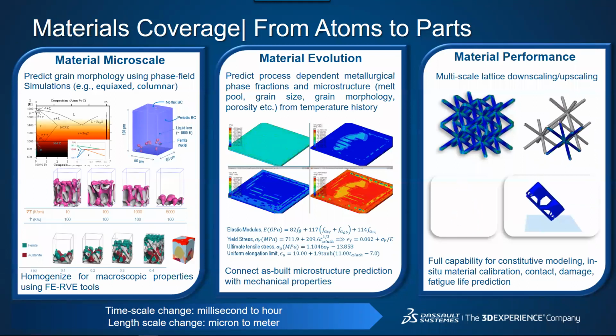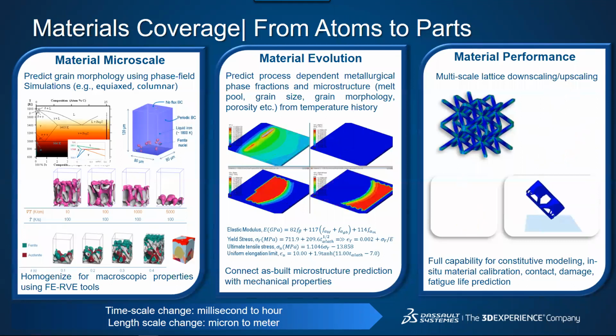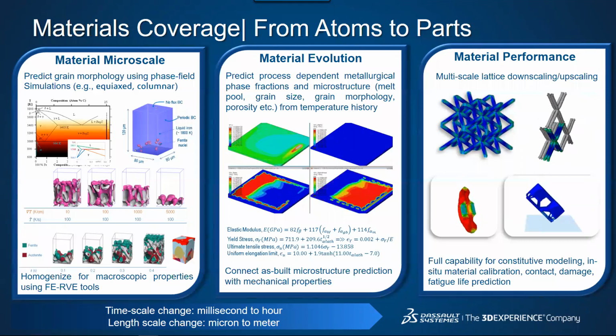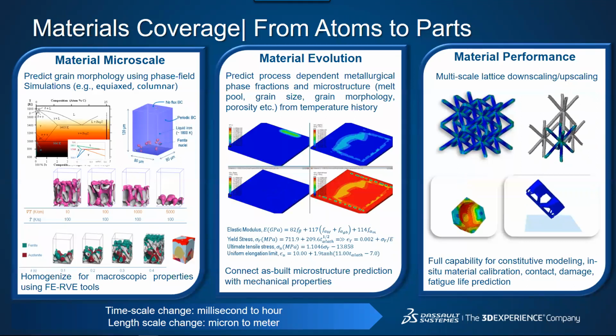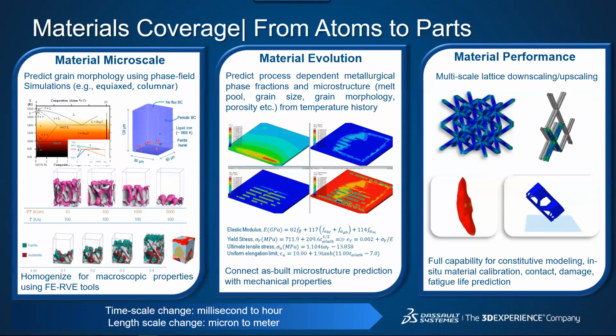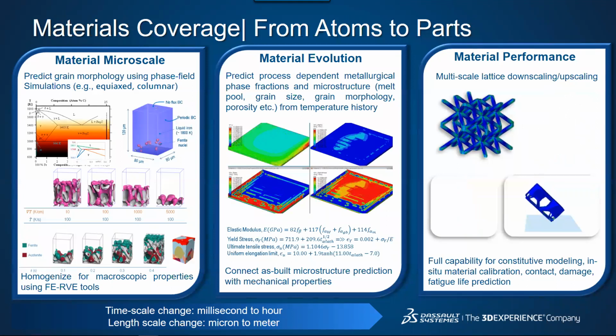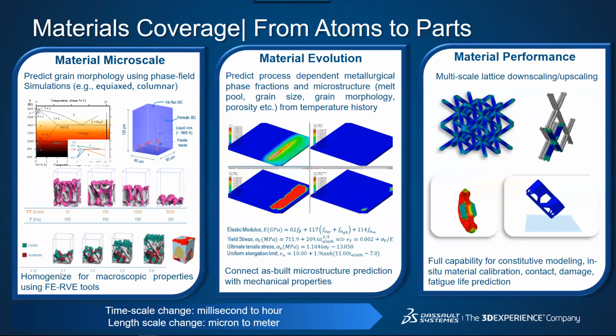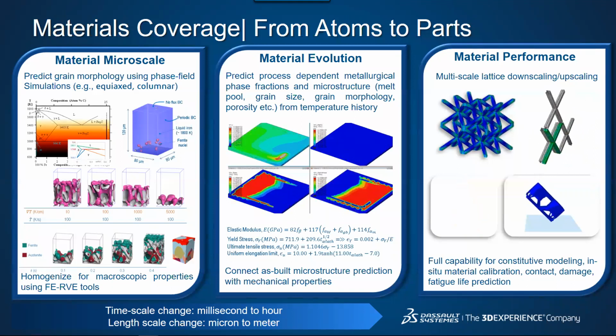So before the print, we have phase field simulations, and this is where the user can study the effect of various alloy additive content on the phase transformation and grain morphology. You can look at different temperature gradients and different cooling rates and see what the resulting phase transformations are, and you could do this for a variety of materials. Dassault again has tools within our Biovia brand for doing these types of simulations.